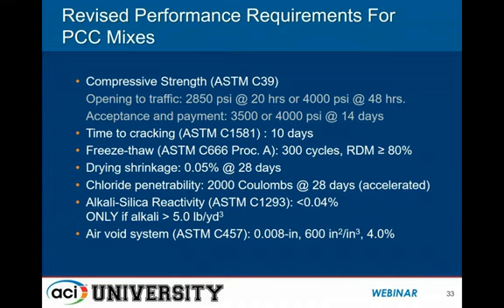The other two factors were assessed carefully, but again, the sense here is that this is a patching system. ASR was also specified, and the air void system. Now, the one point I would mention about the air void system is that it can be a great alternative to actually having to run a freeze-thaw test. Freeze-thaw testing is a long-term test that takes about 10 weeks, and I have yet to run into a construction contract where a 10-week time frame is accommodated as part of the mixture development process. It's really a challenge. The pace of typical projects doesn't really allow us to get that testing in. So what we've had to do in many cases is move towards the air void system. That's a test where we're simply cutting the sample open and looking at the hardened, polished sample, and that can be completed in a matter of days. So really more of a sensible way to go.